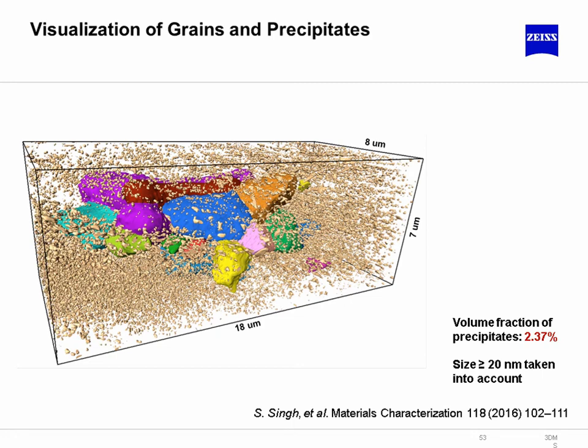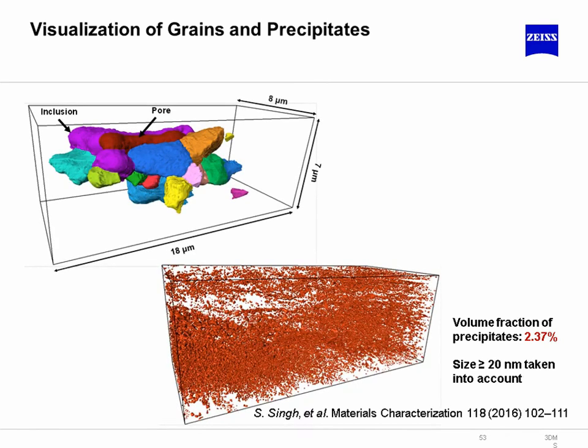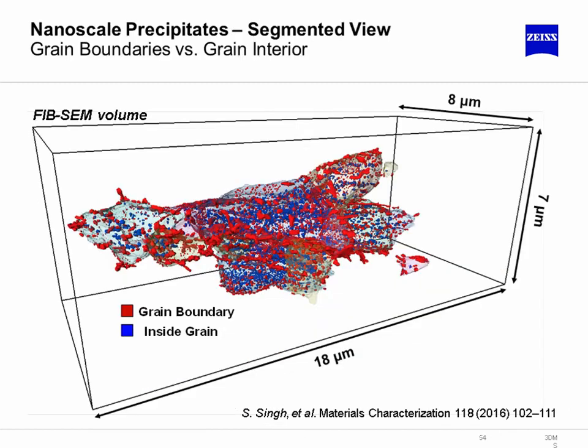This is the segmented volume now of the FibSem volume, showing in color some of the grains and all of the different inclusions. Okay, that's nice, and you can measure that the volume fraction of the precipitates is 2.37%. But what's of most interest is really to get some statistical understanding now of where these precipitates are, and does the shape or size have an influence on where they're located with specific relation to some of the aluminum grains. So that was done for this data set, and that we're centered around this inclusion and void gives us now a symmetric environment in which we can quantify this information.